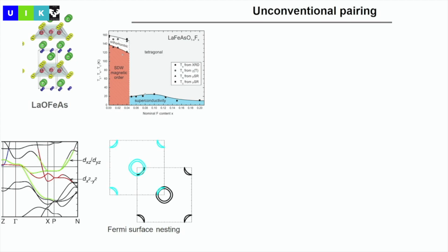And now, if you just follow, here is your Fermi level. If you just follow to draw the Fermi surface, you see that around the gamma point, you expect to have two hole pockets, while here around the X point, you expect to have electron pockets. And this is what you see. This is the gamma point. Sorry for having forgotten to write the K points. So this is the gamma point, and you have these hole pockets around the gamma point that you can see are of different band character. And then you have, at the X points, these electron pockets that can also have different band character.